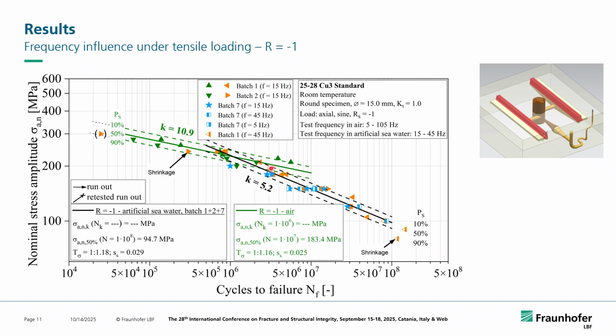We could not really see that there is an influence if you go to 5 Hertz. So we had early failures or late failures on comparable load levels. When you look closer at these results, we have some 45, 15, 45 and 5 Hertz results here, and also on the other side of the scatter band. So our postulation at this stage is that testing at 5 Hertz, 15 Hertz or 45 Hertz doesn't matter. We do not really get an influence, which is a good result. So for further tests, once we get an agreement with the certification body, it will be very favorable to test under 45 Hertz due to time constraints and energy constraints and so on.